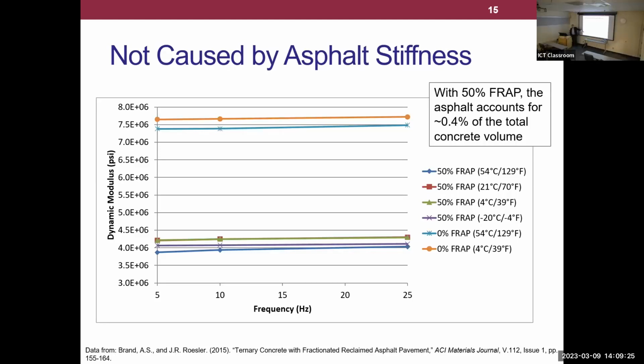Also, when you're using 50% RAP as a replacement of your coarse aggregate in the concrete, only 0.4% of the total volume of the concrete is asphalt. So is 0.4% asphalt really going to be the only reason why you're losing modulus, dropping modulus by 40%? That doesn't seem logical, right?